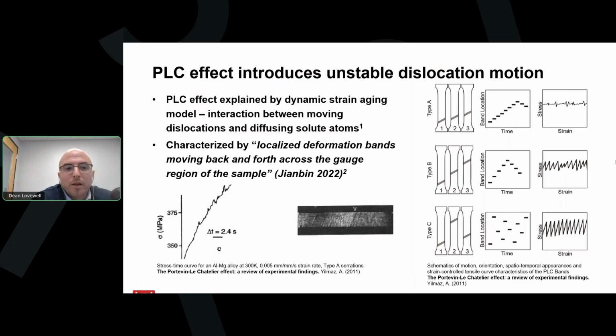This jerky flow is the result of magnesium atoms diffusing through the aluminum matrix, pinning dislocation movement in localized regions of the specimen. With dislocation movement pinned, there'll be a rise in tensile stress, and we observe that in the curve. And that rise continues until the solute atoms become depinned, in which case they flow and the stress is lowered. This occurs repeatedly, and the striations are even visible on the specimen itself.